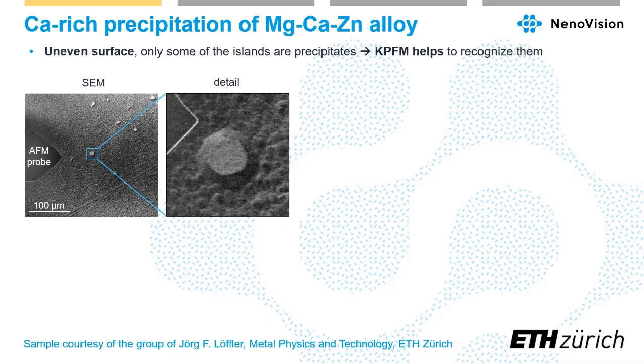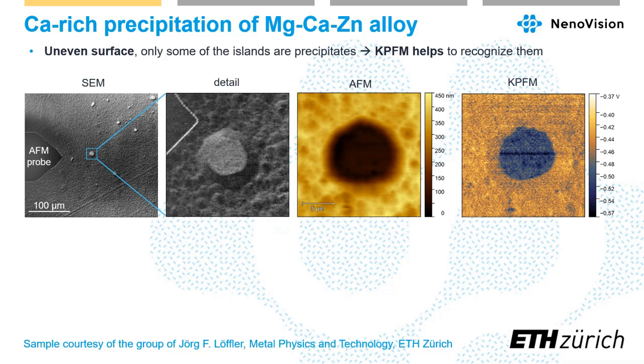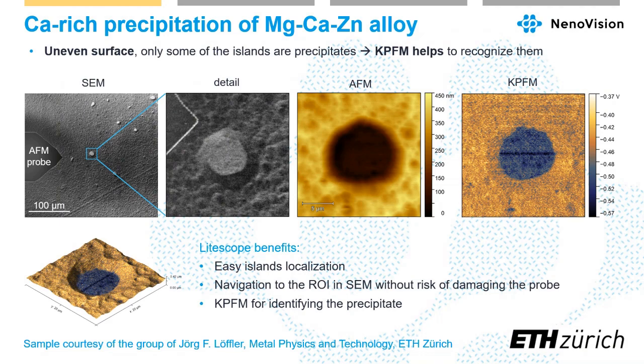There was an uneven surface, so only some of the islands were precipitates, but often we weren't sure which one is precipitate and which one not. So KPFM, the surface potential, is different on the precipitate. So KPFM was able to recognize them. So we measured the SEM, AFM, and KPFM signal, and we were able to easily localize the islands. We were able to navigate to the area of interest with the probe, without risk of damaging the probe when the islands were big. And we were able to identify the precipitate using measurement of surface potential.